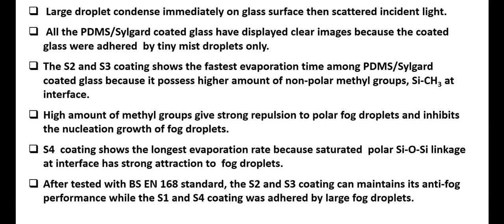These are the tests that have been carried out, the standard test of BS-EN 168, where the S2 and S3 coatings can maintain their anti-fog performance, while the S1 and S4 fail due to the large droplets adhered to the coating. This is how we can see the anti-fog performance with the BS-EN 168 standard testing method. The S2 has 12 minutes, about 50% lower than the other coating systems, S1 and S4.